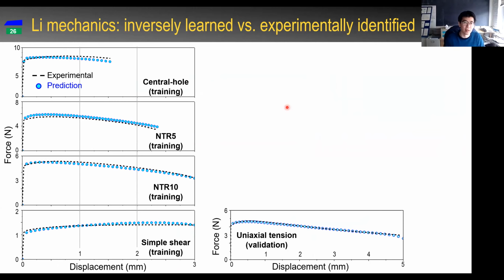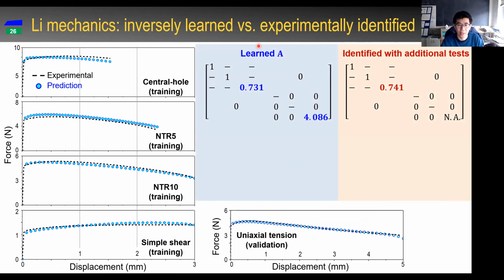Then we apply all the data into the algorithm, and we inversely get the prediction of each single test: central hole, notch tension, different notch tension, simple shear, and uniaxial tension. We use 4 of these as training, and we used one uniaxial tensile test, the simplest one, for validation. And then these are what we learned: the A matrix, which stands for anisotropy. Very interesting. We can, of course, do additional tests to measure this coefficient. These two are very close to each other.